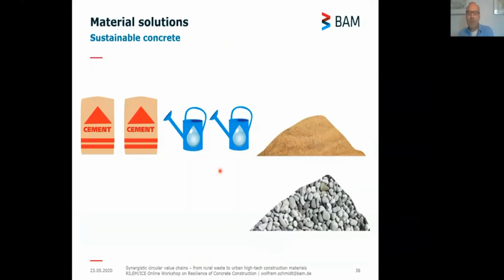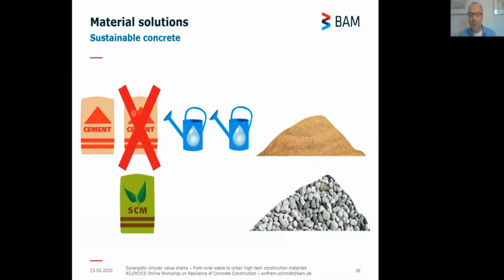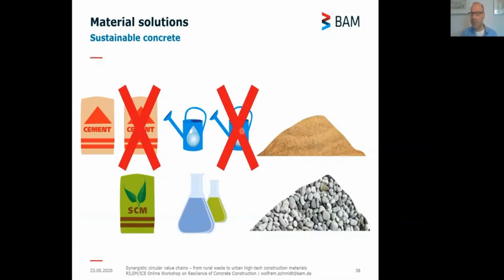At the moment, if we take a look at sustainable concrete technologies, we try to save cement as much as possible and replace it by supplementary cementitious materials. And then we try to reduce the water content as much as possible to tickle out the highest performance out of the binder in the concrete. So we want to reduce the water-cement ratio. And this is what we're doing by using chemical admixtures that manipulate the rheology, that make concrete more flowable.